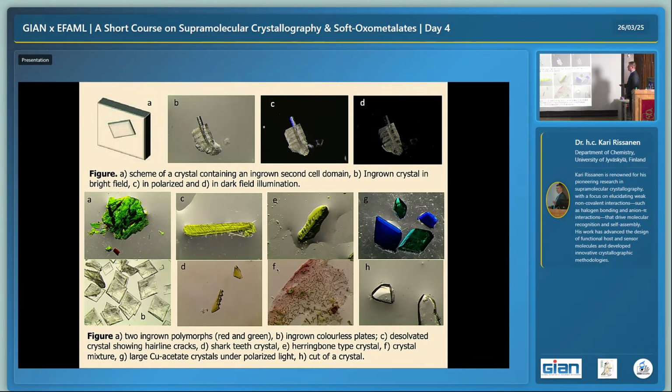Now, here are examples of crystals. This is a nasty case because there are two different crystals. We call it twin crystal. And in here you can see what happens when we use polarized light, that this is clearly not a nice part. It's crystalline, but it's bad. But there seems to be a nice place. So this is a single crystal, this is not.